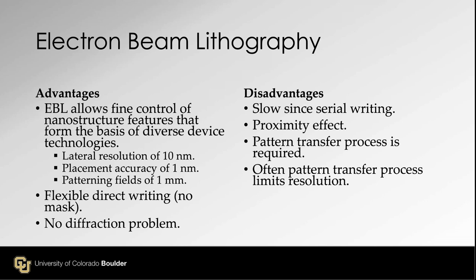Disadvantages of electron beam lithography: it is slow compared with other direct writing methods, because it's serial writing. You expose one area, you move to the next area, and you move to the next area. So it takes a long time if you want to write a 300 millimeter wafer. It's gonna take forever. There's also the proximity effect that can kill resolution. So it's not perfect. And of course, a pattern transfer process is required. This is true for optical lithography as well. However, the pattern transfer is mostly post-processing after the lithography process. This can kill the good resolution of EBL.